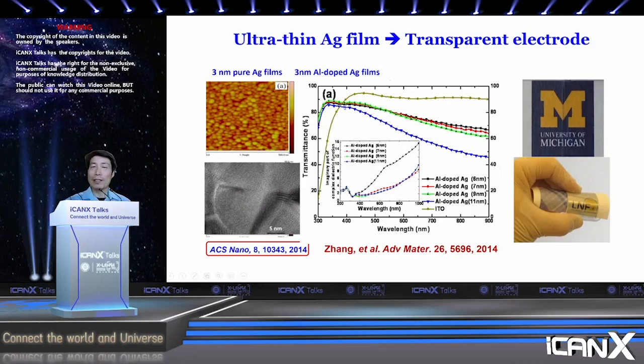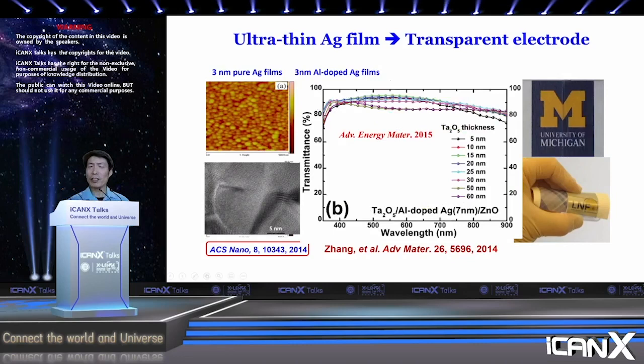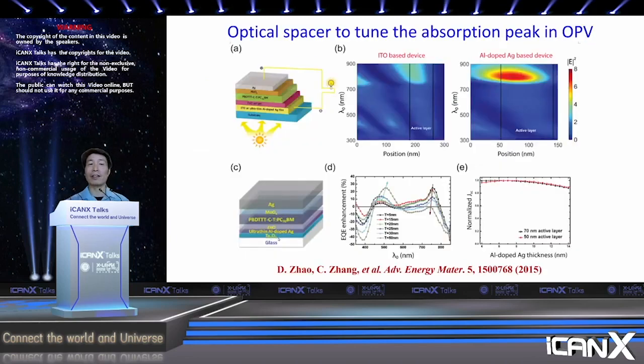But this can be solved, because metal is simply more reflective. So by adding another layer of, let's say, zinc oxide on top of the silver, we make it much more transparent, because the zinc oxide here is acting as an anti-reflection layer. Now, zinc oxide, for those who are working on devices, is also a very useful electronic material. It transports electrons, and that's where we actually use it for making solar cells in that previous work. As well, later on, we showed that you can get even thinner continuous silver film on tantalum oxide. So it depends on the substrate.